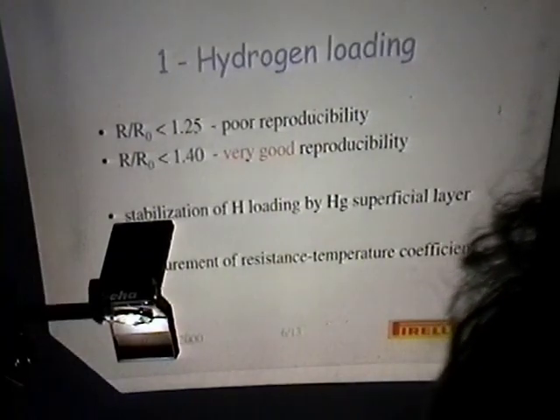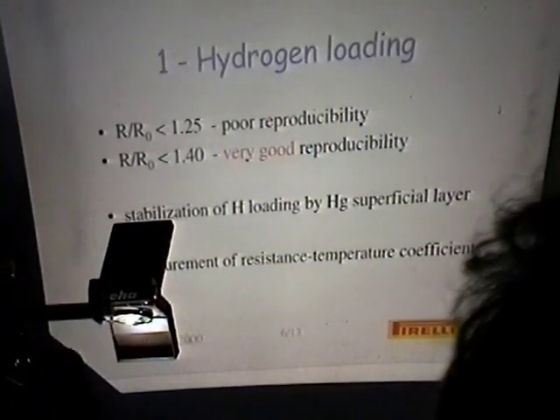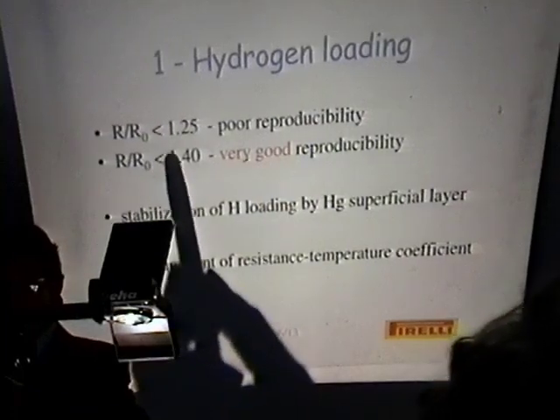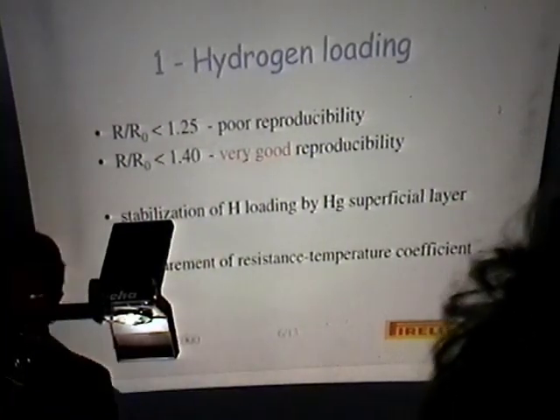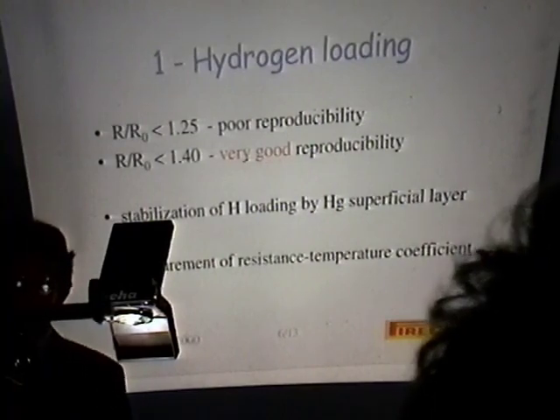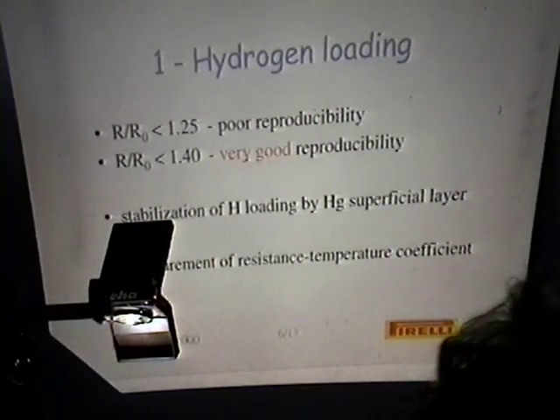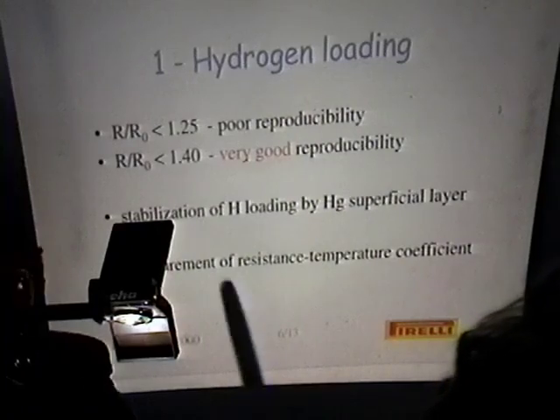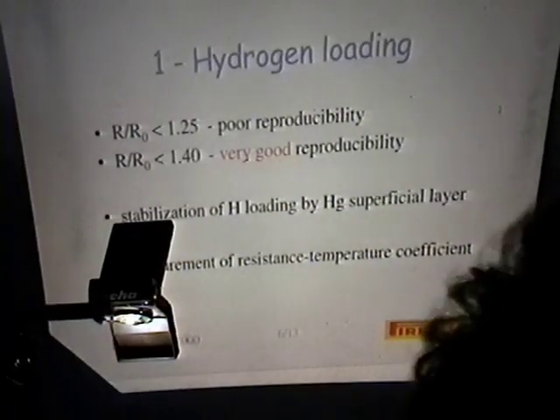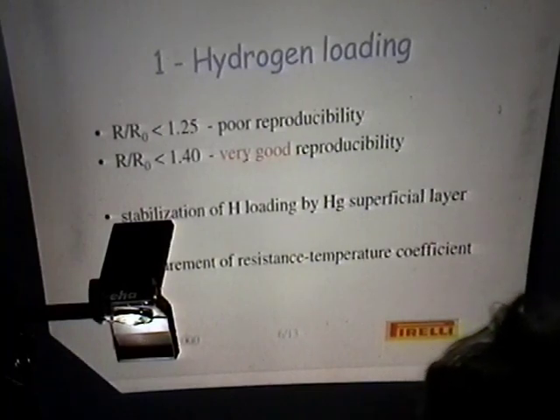The measurement is done using alternate current that is applied through the wires. The first result that I want to present you is about hydrogen loading. I write here that we have reached a resistance ratio less than 1.25, but with poor reproducibility, but a resistance ratio less than 1.4 with very good reproducibility. We can obtain this value almost always.